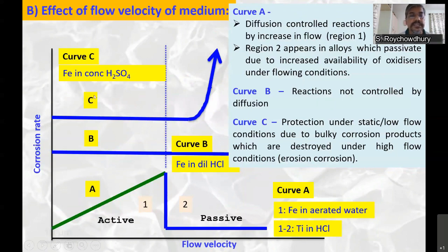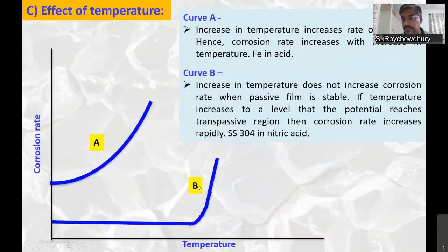Another possibility is like C, where the corrosion rate is low to start with, then beyond a certain flow velocity, there is a sudden increase. This is mainly due to the start of mechanical effects, erosion corrosion, coming into the picture. Similarly, for example, iron in concentrated H2SO4. It forms a stable or protective ferrous sulfate layer, which gets removed at higher flow velocities, exposing the base metal and further corrosion occurring.